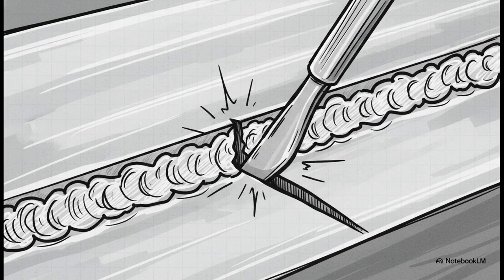And making this specific heat treatment mistake with certain stabilized grades of stainless steel, like SS321 or SS347, results in this chillingly precise type of failure. In the industry, they call it a knife line attack. Since the chemistry breaks down right at the boundary of the weld, the corrosion slices through the metal in a microscopic, razor-thin line that runs perfectly parallel to the joint. It literally looks like someone took a surgical scalpel right to the heavy steel.